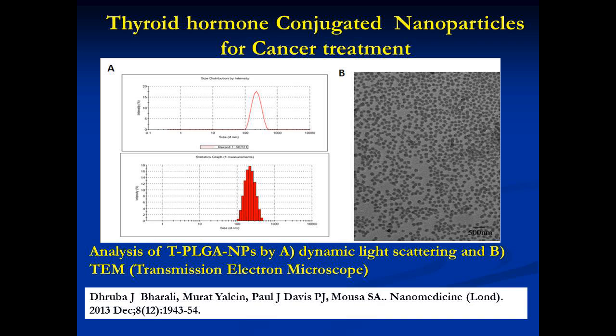We characterized the nanoparticles with dynamic light scattering and transmission electron microscopy. You can see here the size we can restrict. We can manipulate the size, but the favorable size for us was around 200 nanometers or less than 200 nanometers. Both were confirmed by dynamic light scattering and transmission electron microscopy.